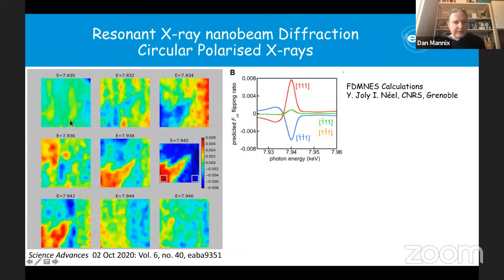So what we have done here is some more scanning diffraction at different energies. We go away from the absorption edge down here, and essentially we can't see any contrast at all. Then we start to get contrast as we move in towards the absorption edge. The first thing that happens is you start to see something arise, but it's actually a negative contrast, not a positive one, down here. That agrees with the theoretical prediction that first of all it will go negative, and then as you increase the energy it will go positive and then go away again, as you see down here. So this agrees perfectly with the theoretical calculations and gives us very strong evidence that what we are looking at is in fact magnetic domains in these material systems.